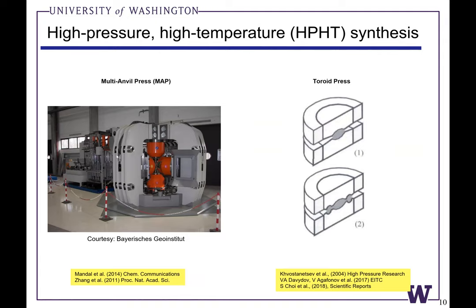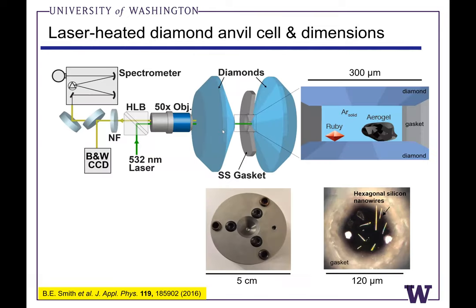One challenge of the multi-anvil press is that it's hard to get optical access to the multi-anvil cell chambers. It's hard to do, for instance, Raman spectroscopy in situ in these multi-anvil press instruments. It's also frequently difficult to use inert pressure media like noble gases in multi-anvil presses. But there's been some very nice work recently demonstrating the synthesis and also doping of nanodiamonds using a multi-anvil press approach. And this is very complementary, I would say, to the laser-heated diamond anvil cell.